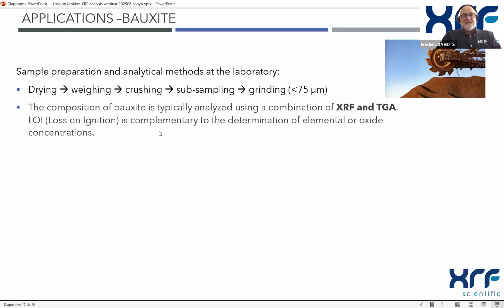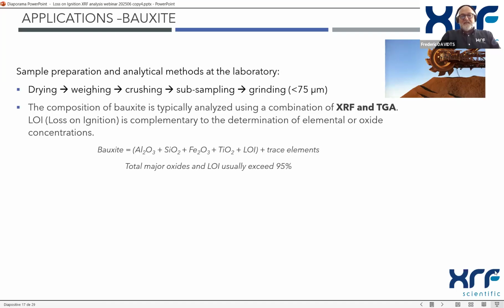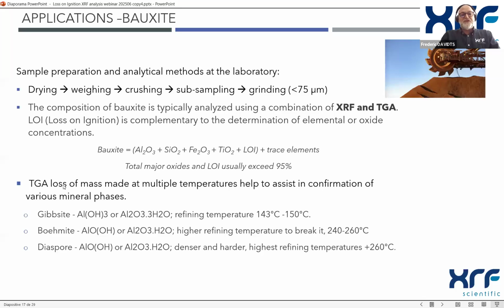So again, as explained, the determination of LOI is complementary to the determination of element or oxide composition. By XRF, we are able to analyze the major oxides. And if we add the LOI, we usually exceed 95% of the bauxite content. Also, the TGA loss can be made at different temperatures to assist in the confirmation of the mineral phases. And this is highly important to know at which temperature we will do the refining, depending on the phase we have.